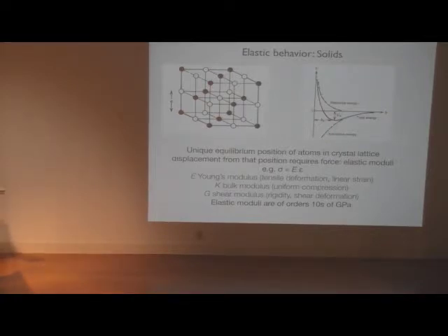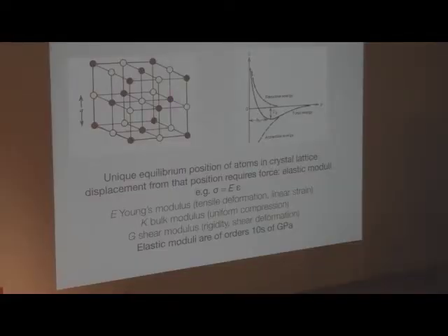Of course, as you increase the temperature, you probably know that well, the atoms begin to vibrate, essentially vibrate in this energy minimum. And you can see that the energy minimum is not symmetric, so the vibration is not harmonic, like when you take the spring and you elongate it and vibrate. As long as you keep tapping it with the same force, it'll vibrate harmonically. Here the atoms vibrate anharmonically, and you might hear me use that term, anharmonic temperature dependence, right? The higher the temperature, the larger the deviation from the equilibrium position.